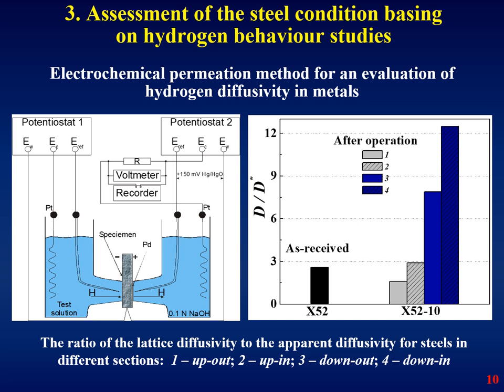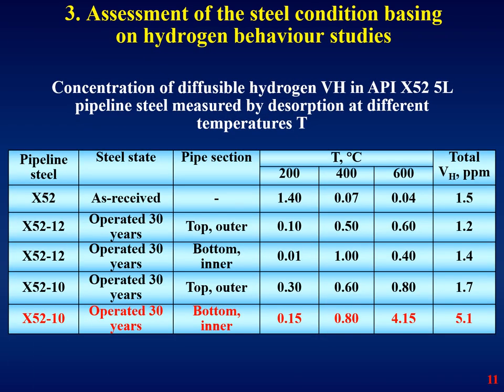On this slide you can see that the exploited steel is distinguished by a high ratio of diffusion coefficients, indicating a higher level of micro-damaging. Using the hydrogen extraction method, it was found that in the case of steel in the initial state, most of the hydrogen was dissolved at a low extraction temperature of 200°C, whereas the operated steel is characterized by high temperatures of hydrogen release, indicating hydrogen trapping of high energy.